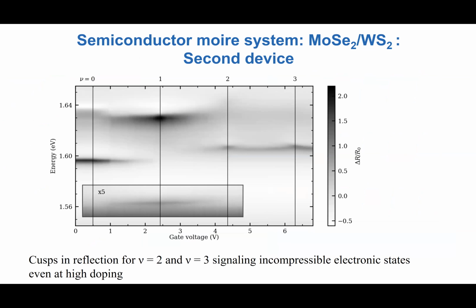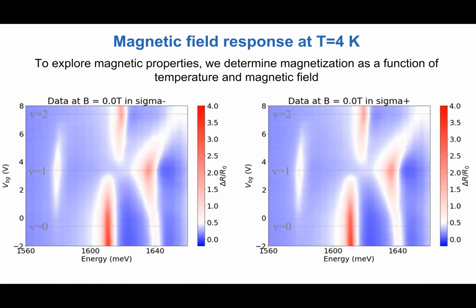And this is another device showing similar features. And regarding this incompressibility and similarity to the integer quantum Hall effect, you see that this resonance at nu equals 2 and 3 exhibits these cusps. And this is actually also seen in other material systems, this relatively weak signature of incompressibility of electrons on the exciton spectrum. Okay. But that's not what we are looking at.